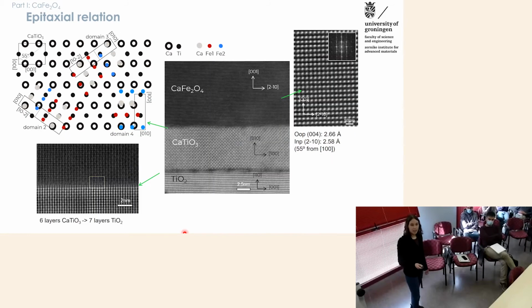And to understand this, we have to look at the structure of our intermediate calcium titanate layer. So in the TEM, we can really see that the interface between titanium oxide and calcium titanate is quite ordered. We can see that for 6 columns of calcium titanate, we have 7 of titanium oxide, which orders in a perovskite structure.